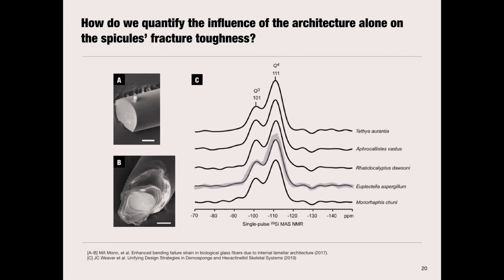So the Euplectella spicules I've been looking at are shown here. And these are spicules from other sponges that are related to Euplectella. Some of them have layers, but one that doesn't are these spicules from a sponge called Tethya aurantia, and that's shown in figure A, a cross section. So you can see it's monolithic, but it is chemically basically the same. These curves are just vertically shifted to show the differences in them. So the tricky part is that these spicules are even smaller. They're about 30 microns in diameter, and they're only about 1 millimeter long.